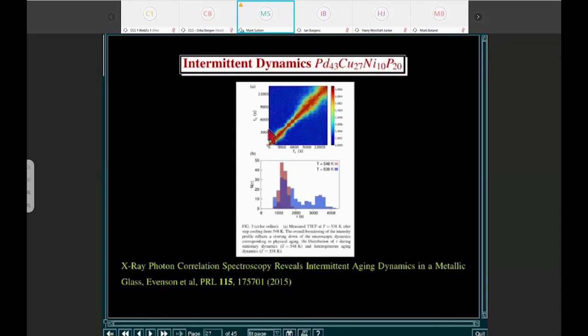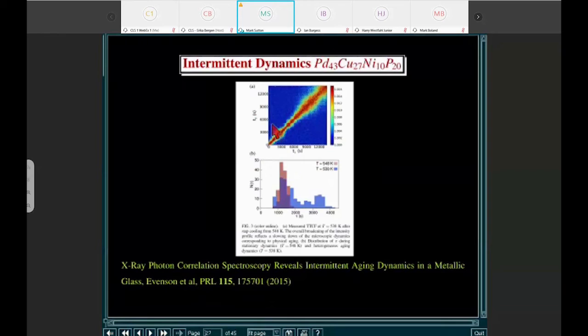We can see the fact that there's intermittent behavior, and this is an example of a metallic glass, and you can see the fluctuations as a function of time are intermittent. So sometimes they're slow, sometimes they're fast, and you can look at the statistics of how these go by looking at what happens in your two-time correlation function.